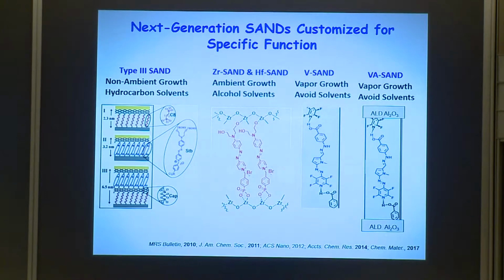But also, it's a wonderful exploration area to let your chemical intuition develop new kinds of materials. So these all have silicon layers. You have to do it under nitrogen. These use alternating metal oxide, and again, always an organic pi system, metal oxide. And Alex, you may remember this was originally an NLO chromophore. And these you can grow under air, and I'll show you some of the properties. Now, if you don't like solvent at all, these are two. We called this V-sand, and this has little ALD alumina cappings. These are very good if you want to avoid solvents.